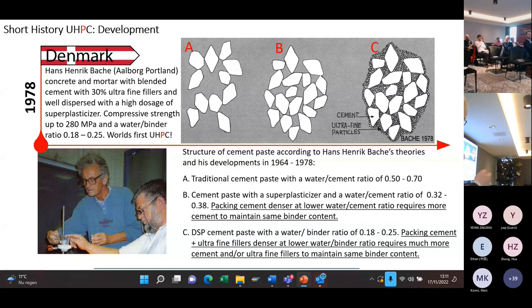After the first tests, he came in contact with a Norwegian colleague who had a lot of micro silica, almost for free because it was a waste product. So he started to use this because his experiments with very fine cement didn't work — when you make cement very fine, you get fast reactions and you cannot control it anymore. But micro silica is less reactive than cement; it starts to react later. Also, the particles are round while cement particles are angular, so you can make an optimum packing between the cement particles with micro silica.